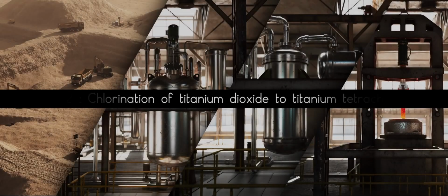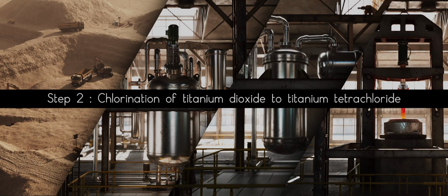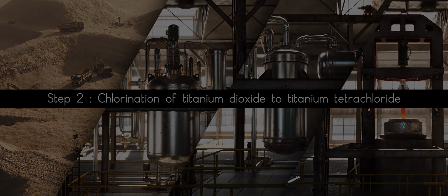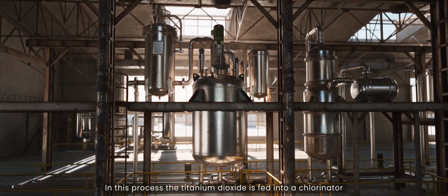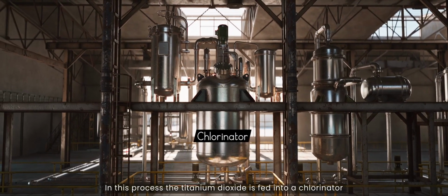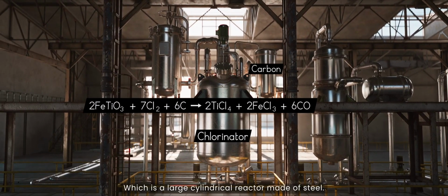Step 2. Chlorination of titanium dioxide to titanium tetrachloride. In this process, the titanium dioxide is fed into a chlorinator, which is a large cylindrical reactor made of steel, heated to a temperature range of 800 to 1000 degrees centigrade. Chlorine gas is then introduced into the reactor, where it reacts with the titanium dioxide to produce titanium tetrachloride.